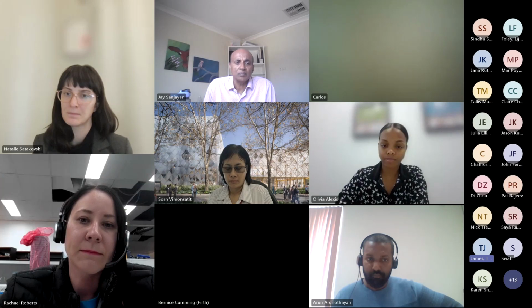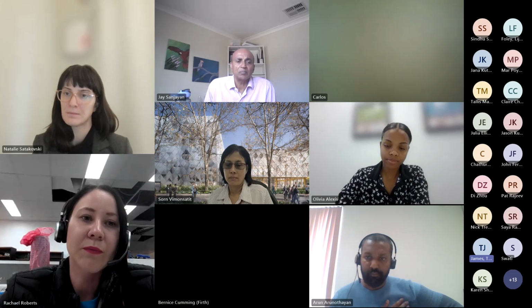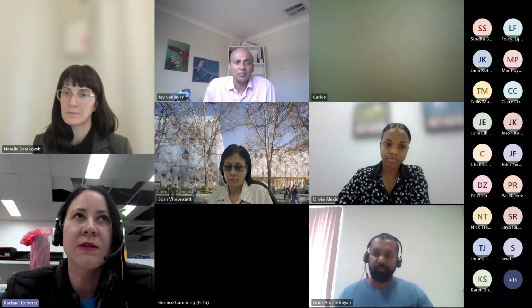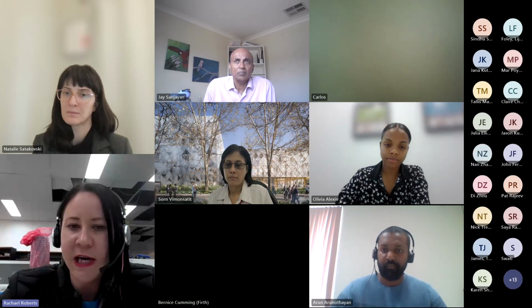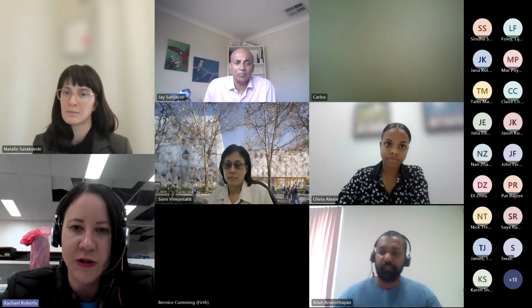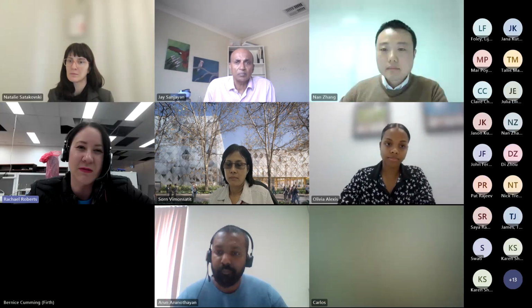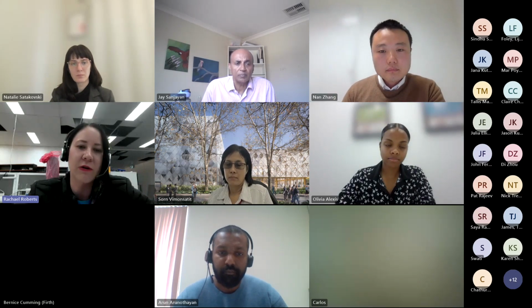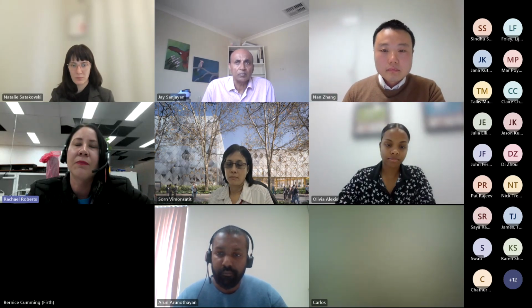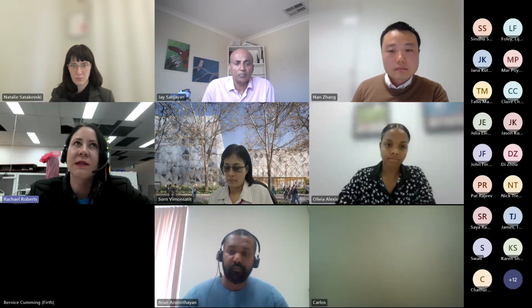Okay, so what about the concentration? Because if you're using a large amount, it's typically a bit more concentrated than, as you said, paint that you'd use in your house. Is that a concern at all? I don't imagine so. I think Jay's research is capped at 30 litres per cubic metre. So that's still just 3% per cubic metre of concrete. It isn't an enormous amount of paint when you think of the volume of concrete being poured. So yeah, it's not necessarily a concern.